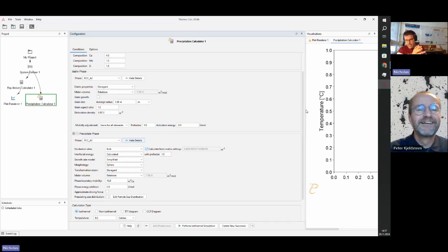If you do a thermodynamic calculation, thermodynamics is relatively well established. You can say that's relatively quantitative, right? Then if you move to Dictra, you've got the thermodynamic driving force for diffusion. But on top of that, you've got the mobility and the diffusion models, which have uncertainties. So the thermodynamic database and the mobility database have uncertainties, and the models have uncertainties. So with Dictra you're already starting to have a lot larger uncertainty. And now with nucleation and growth, you've got even more uncertainties, right?